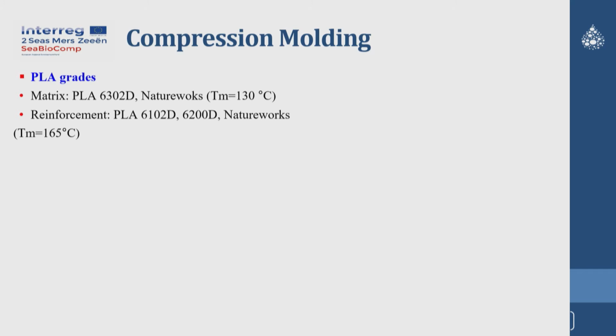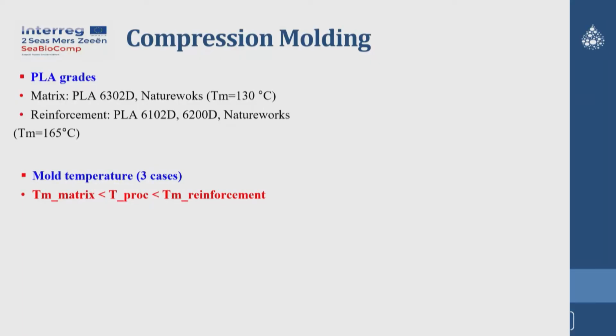So the processing temperature should be between the low melting temperature of the first one and the high melting temperature of the second one. You can see that the low melting temperature is 130 degrees Celsius and the high melting temperature is 165 degrees Celsius. So the process temperature should be between these two temperatures. We have a process window of about 30 degrees Celsius. And then we selected three mold temperatures: 145, because 135 and 140 were too low to melt the matrix phase, then 155 and 165.